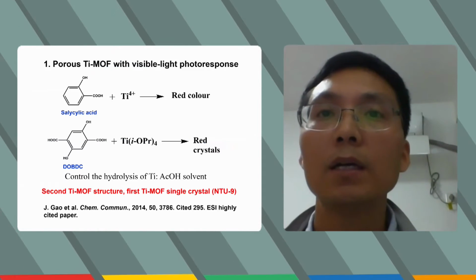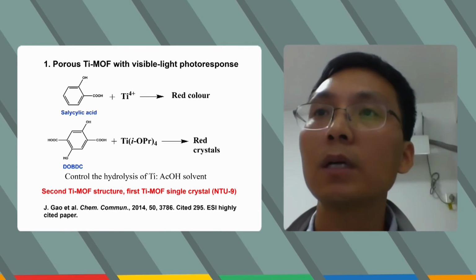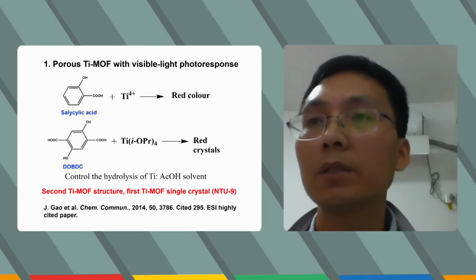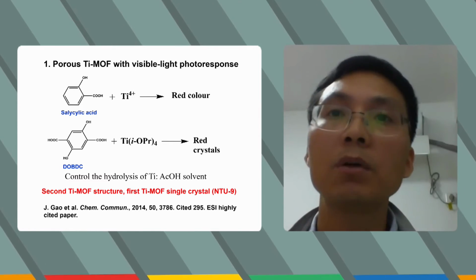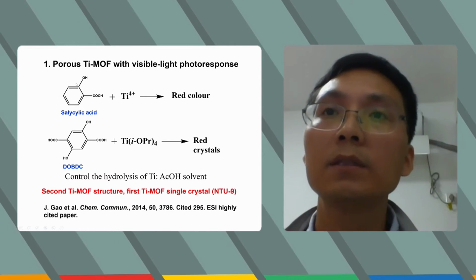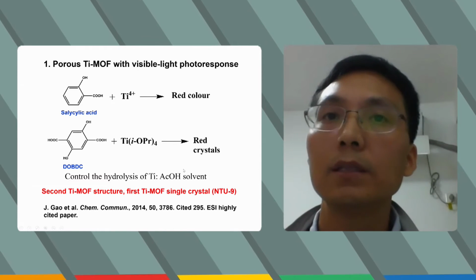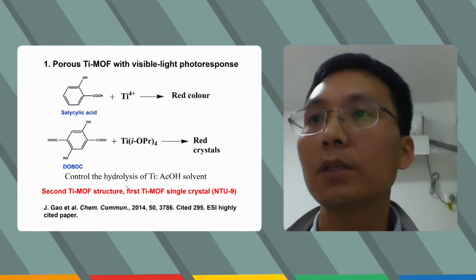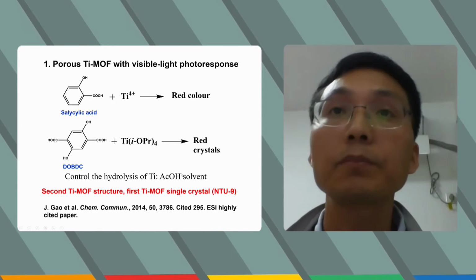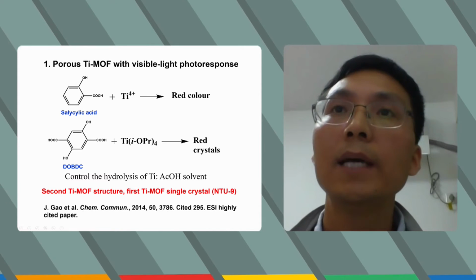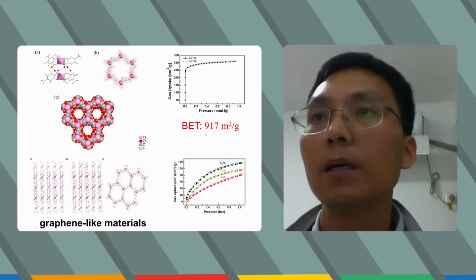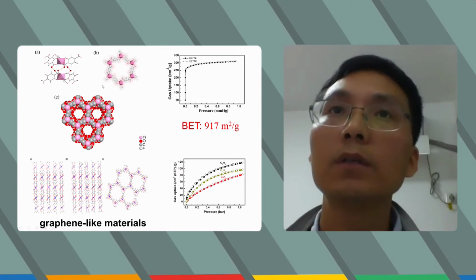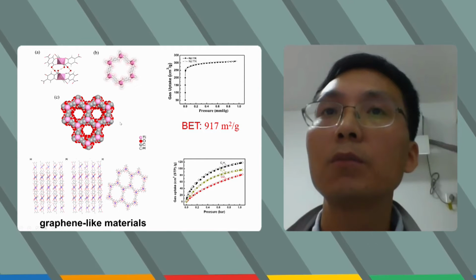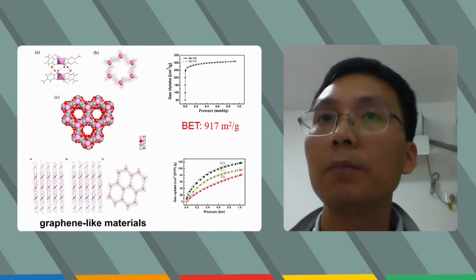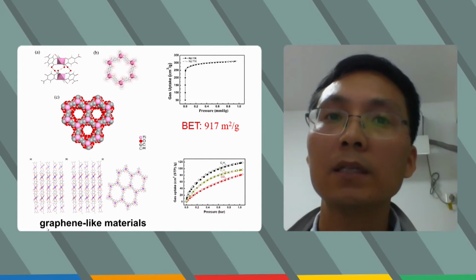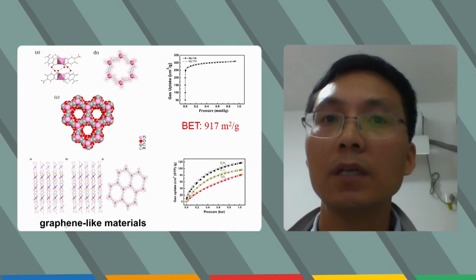The first one is NTU-9. This is my work studied when I was a postdoc at Nanyang Technological University, Singapore. In this MOF, the color is red, and this is the first single-crystal titanium-based MOF. We can see that this MOF has a large surface area, about 900. Also, this MOF is two-dimensional. The layers are stacked by hydrogen bonds. So we call this a graphene-like material.